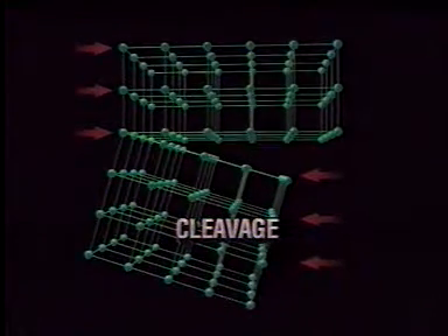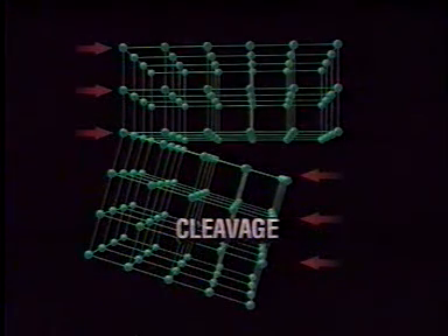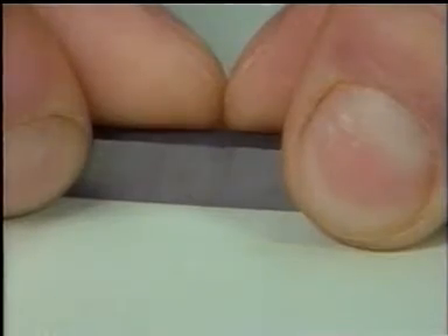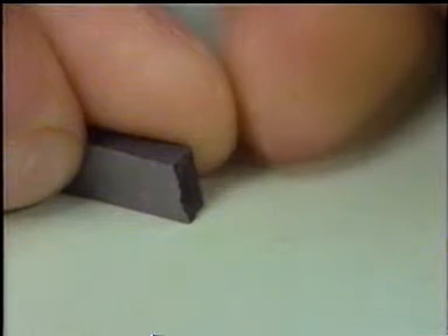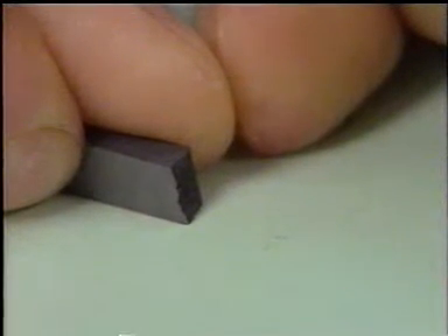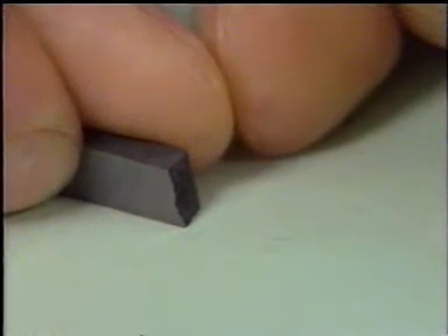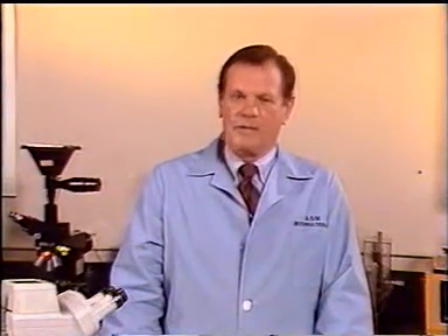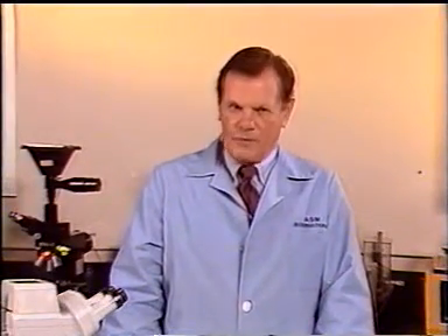Cleavage on this atomic scale means splitting. A very rapid split or separation of the crystal lattice could be expected along a side or a face of the cell. This cleavage fracture occurs before yielding and permanent deformation can occur. Cleavage is a brittle fracture. Actually, cleavage is only one of two different brittle fracture mechanisms. The other, known as intergranular, will be discussed later in the program. For now, it's easier to consider only shear and cleavage as the fundamental types of single overload fracture.